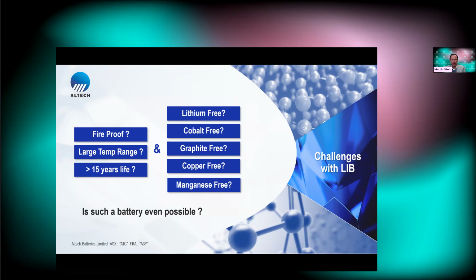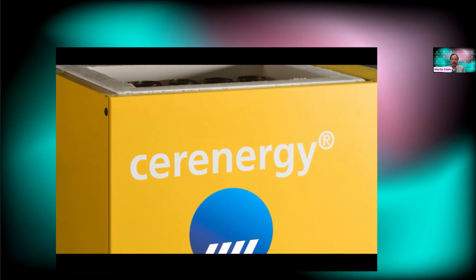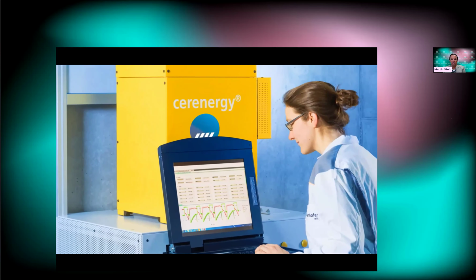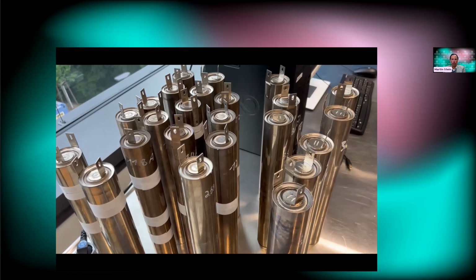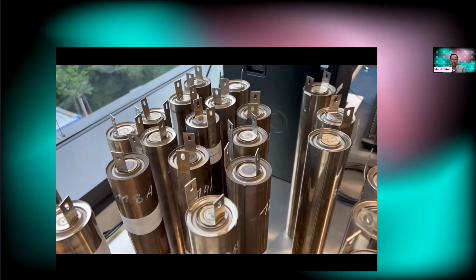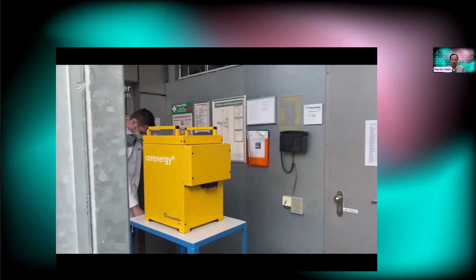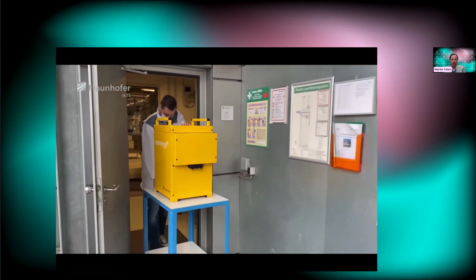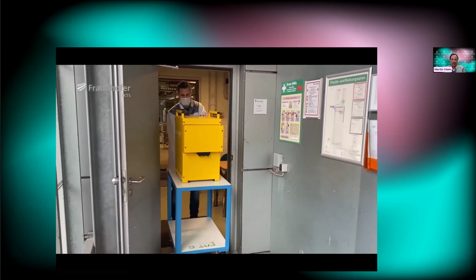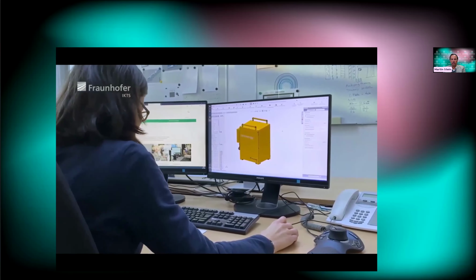So is there a battery technology that is completely fire and explosion proof, that has a large operating temperature range and can last for more than 15 years and doesn't have any lithium, cobalt, graphite, copper, or manganese? Well, here we go. This is Altech's battery technology. It's called the Cerenergy battery, and it meets all of those criteria. It doesn't use any of those raw materials. It's fire and explosion proof, and it lasts for a long time and can be used in -40 to +60.